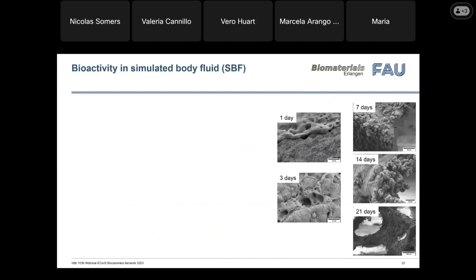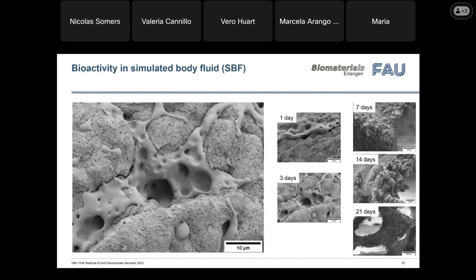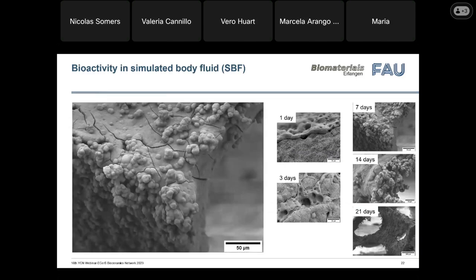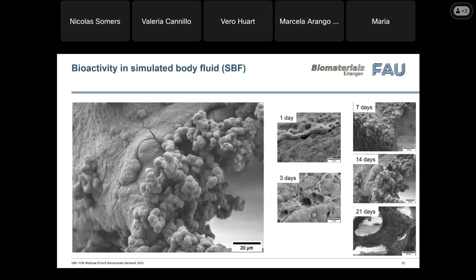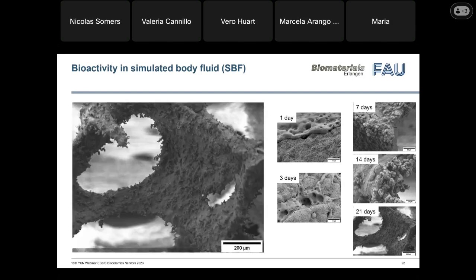We also performed the bioactivity test to see if there was an effect of the coating or the presence of honey on the formation of the hydroxycarbonate layer. Here we can see that after 1 day or 3 days, mainly the degradation of the coating is happening. But after 7 days, we can already see good coverage of the apatite layer, which we could also observe, of course, after 14 days and also 3 weeks of immersion in SBF.